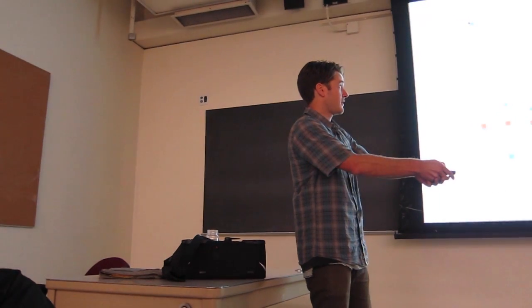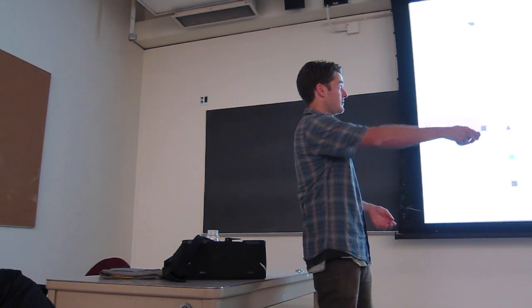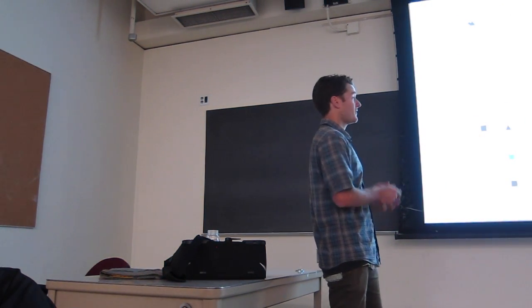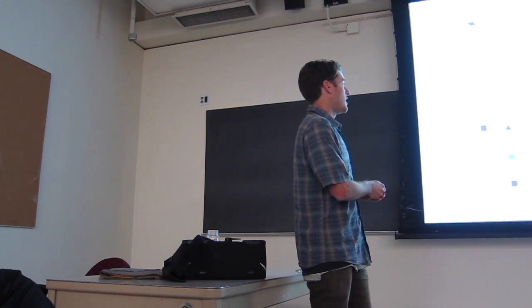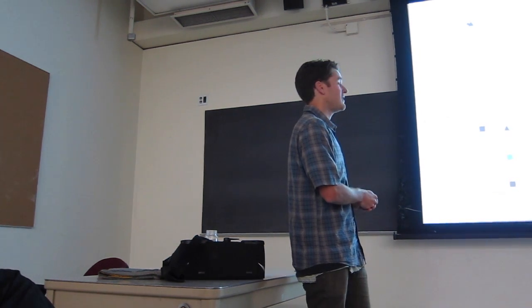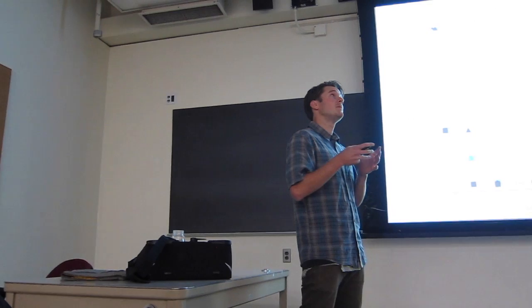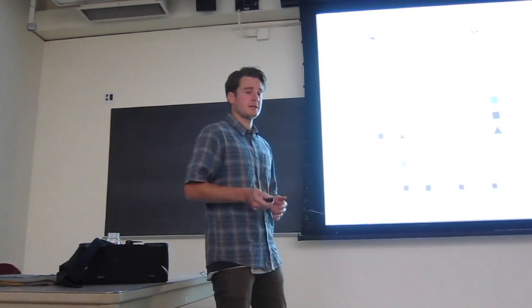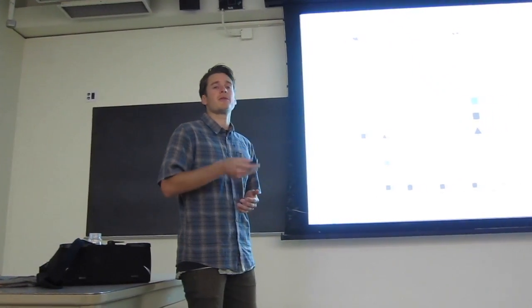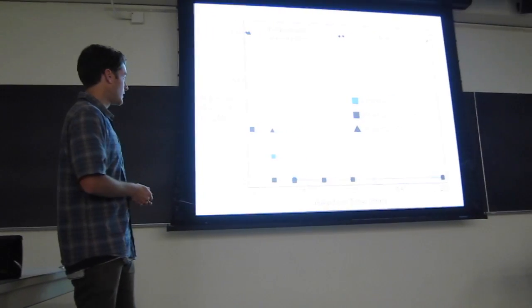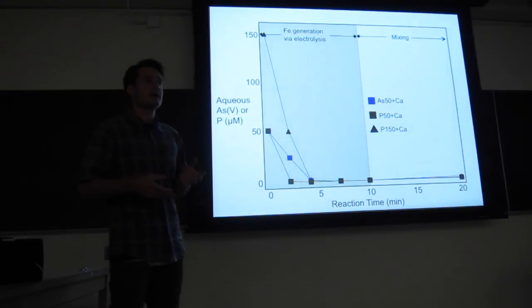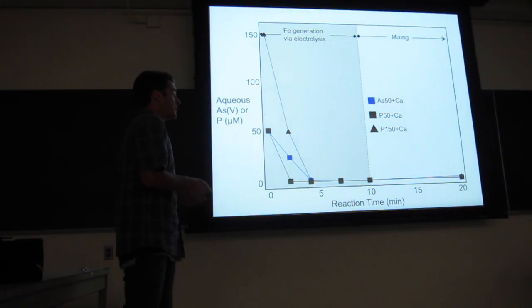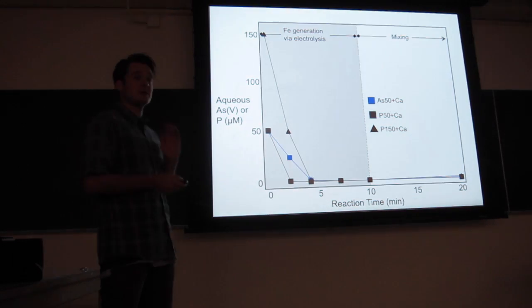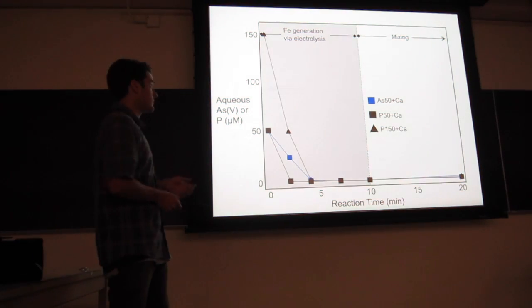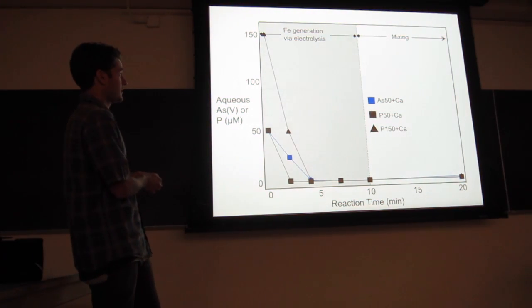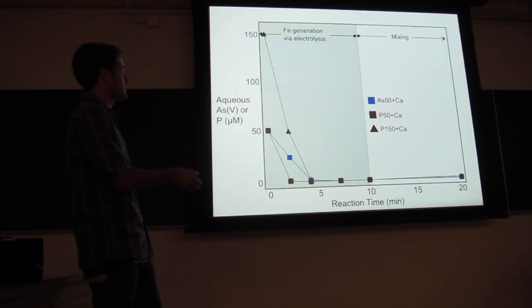So for the phosphate concentration series, we see that phosphate is depleted even with less iron required than in the arsenic concentration series. And that's consistent with our batch uptake experiments as well. So since in this technique we control the current, we know very precisely how much iron we've added into the system. And so at this largest phosphate concentration, we can actually calculate the solids ratio.